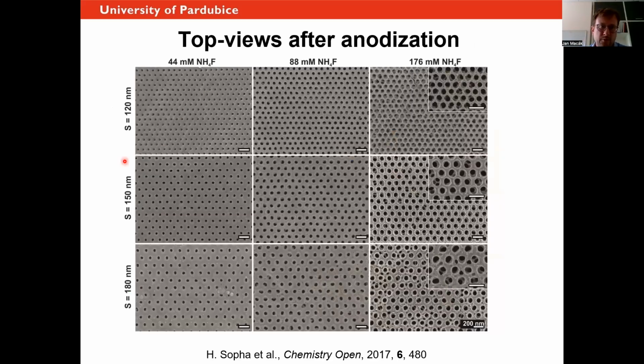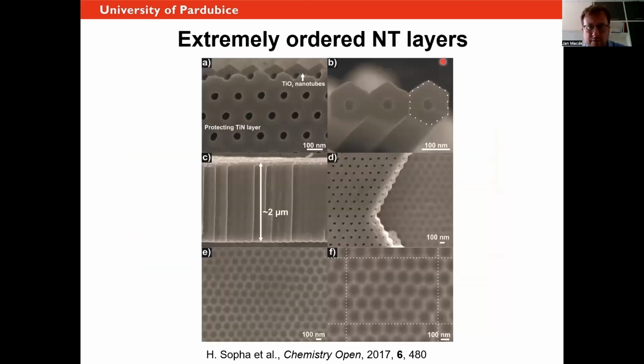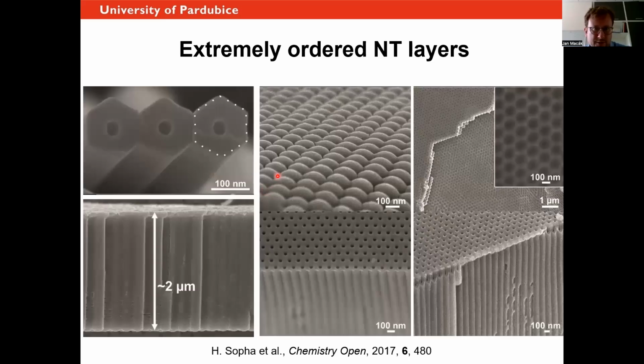So at the end, we tried different distances between the holes, different concentrations, and we ended up with something which looks like this. So we got not just extremely ordered tubes at the bottom, but really almost perfect, excellent arrangement of the tubes at the top. And there is still this titanium nitride layer, which is 3 nanometers thick, but it doesn't really bother us. It doesn't change so much. And you can also see throughout the layer thickness that it is really nicely homogeneous here, some 4 images. So looks great, right?